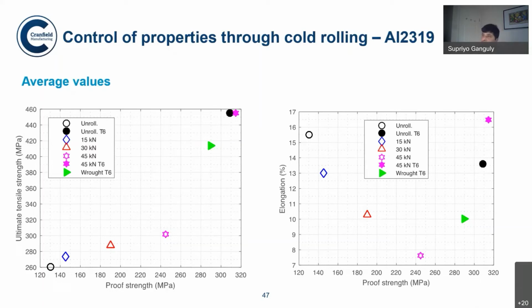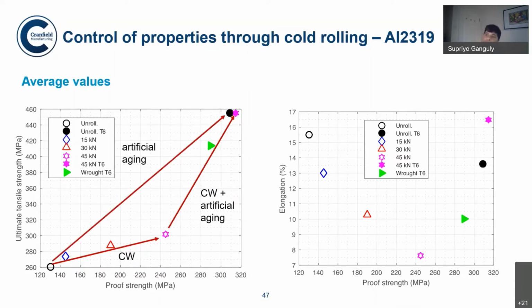aging. And you can see here that the cold work, which is once again the black circle, will increase the strength to some extent, and cold work plus artificial aging can take it to a strength which is more than the wrought alloy. The wrought alloy was shown by the green triangle, and you can see here that the strength has increased tremendously. However, when we do artificial aging directly without doing any cold work, then also you can achieve a similar level of strength. And this is a very interesting observation, as you will see in the next